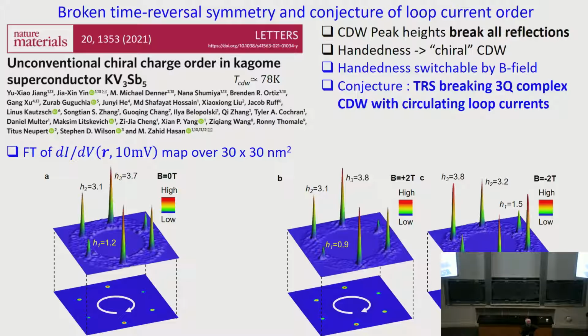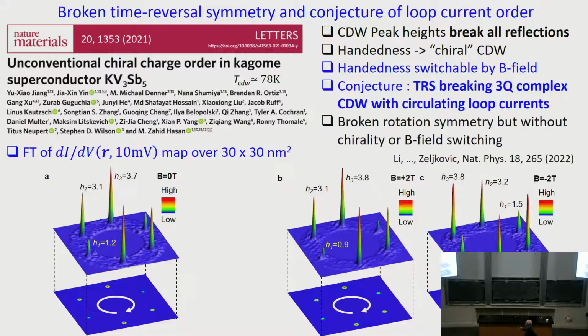You get people who can repeat it, people who cannot repeat it, including my own colleague, Ilya Zakovich's group. They took the same sample and did this experiment, didn't see this. Right? And also, it's just not so clear what it means to have these peaks of different height. Well, in between, a lot of the experiments that probe directly time reversal symmetry breaking, such as optical Kerr rotation, circular dichroism, some of them see, obviously, time reversal symmetry is broken. Some would conclude, no, they didn't see any signal.